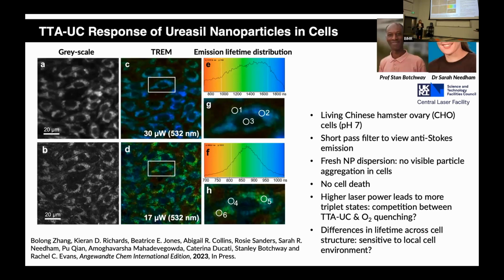And what we used then is a short pass filter to look at the anti-Stokes luminescence. And so our color differences here are just due to differences in lifetime across the cell structure. And so what we see is, first of all, you get quite different levels of different lifetimes across the structures. You can get different distributions depending on the power density of our excitation source. So as I said, the power density is super important because it determines the number of triplet states you have. We've got competition here because we can't exclude oxygen. It's in a living cell. So now we have a competition between TTA-UC and oxygen quenching.